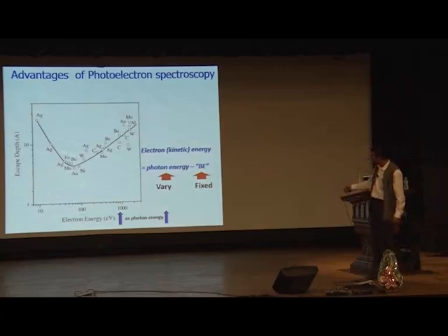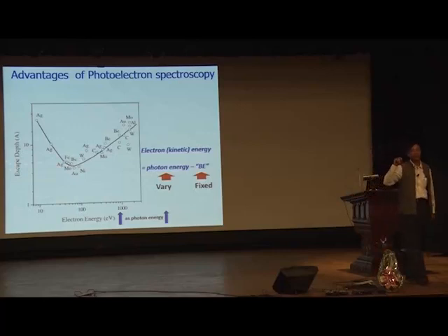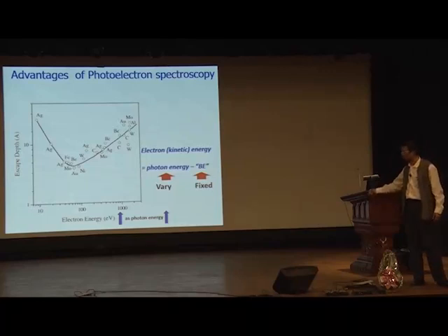And even more important is to notice that the minimum is on the order of some 5 or 6 angstrom, which means that the photoemission signal that you're getting is typically 2 or 3 times the escape depth, because it's not a step function but an exponentially decaying function, the probability of coming out. So you are going to see only the top 5, 10, 15 angstrom if you choose the photon energy there, the electron kinetic energy there.